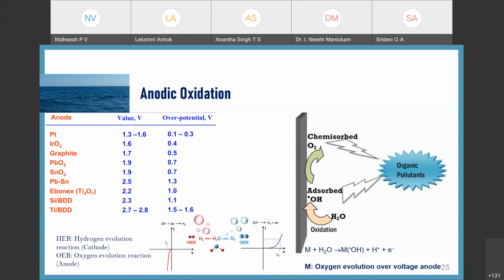But when we applied it to real wastewater, like mixed industrial wastewater or textile industrial wastewater, the concentration of chloride is very high and it contains a lot of other ions. So you know that wastewater is a highly complex system. Then once we tried with mixed industrial wastewater, that means CETP influent, the chloride concentration itself is around 9,000 milligram per liter. There we saw some reduction in chloride content, 9,000 to 5,000.